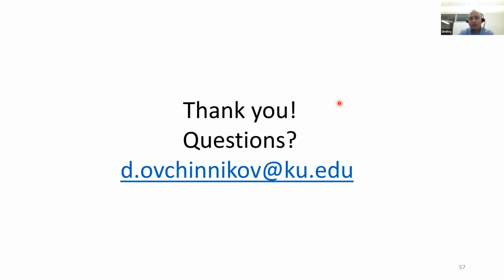We struggled in the beginning because this is a difficult material to work with. I probably made it sound easy, but it's actually not. My understanding is that the groups, including us, who managed to develop it rely on very careful lithography. When you do lithography, it's important not to expose the material you patterned to air, so we try to do it inside the glove box. Number two, your evaporation should be careful, so rates should not be very high. Number three, us and also the Harvard group, and I believe Yambo Zhang in Fudan, we now all use stencil masks. Instead of doing lithography, you have a stencil mask which you align with electrodes on top of the sample, and this allows more careful fabrication. But again, you need to protect your sample all the time. That's the key.